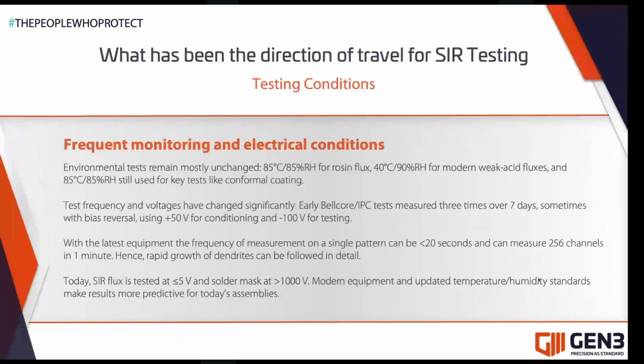So what's been the direction of travel for SIR testing? Some of the conditions: environmental tests remain mostly unchanged. Generally it's always been 85 degrees centigrade and 85% relative humidity for rosin flux. Then for modern weak acid fluxes, generally it's tested at 40 degrees C and 90% relative humidity. And for conformal coatings, generally it's at 85 again.